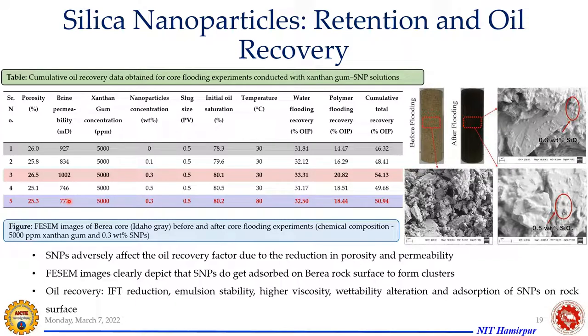So you can see, as per the literature, we have studied this nanofluid flooding, and we have got an overall recovery of around 50.9, which includes 18.5 from your polymer flooding and 32.5 from your water flooding. So this is at higher temperature, and when we are at room temperature, the recovery was pretty high, that is 54.15, giving 33.3 by water and 20.8 by water polymer. So this is how we have identified the optimum formulation.